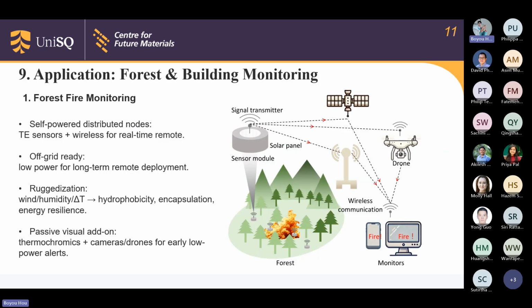This page shows how groups use self-powered thermoelectric nodes in forests. Small thermoelectric patches sit on poles, trees, or fence posts. When a hot front passes, the patches make a direct voltage and a tiny radio sends an alert. Because the nodes use very little power, they work off-grid for long periods. Some teams add a small solar panel only for the radio and the gateway. To survive weather, the coatings are made hydrophobic and encapsulated, so wind, humidity, and changing temperature do not break the signal. Data can travel by cellular or satellite to a phone or a dashboard.